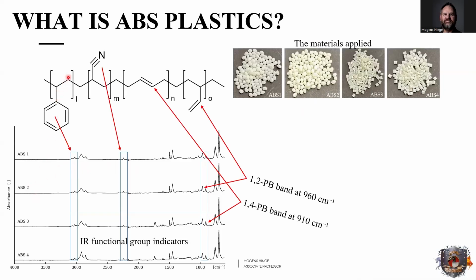So if we take the drawing from before, then I'll have some IR functional group indicators available. So first, we have the polystyrene. This benzene ring that we have here, this aromatic system, will give peaks here just above 3,000 wave numbers. Besides this, it also gives peaks at 1,600, but also these 2 peaks down here at around 700 to 800 reciprocal centimeters. So we use these for reference. So we always reference our relative amounts to the polystyrene phase. Now, we also have the acrylonitrile. This group here has a very nice peak just here, as you can see across the different vendors.